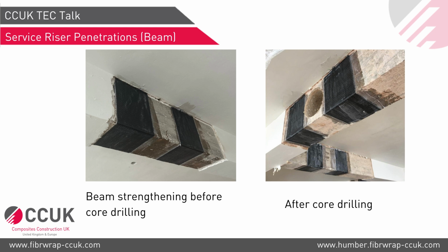The reason for doing this strengthening prior to coring is that right now there is no damage to the existing reinforcement and everything, so FRP could remain as it is. But as soon as they core it and cut a rebar, the FRP will be stressed, so that any additional stresses will go into the FRP, so that you utilize the FRP completely in that way.